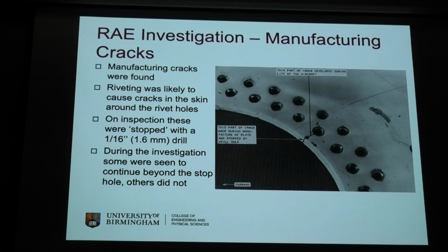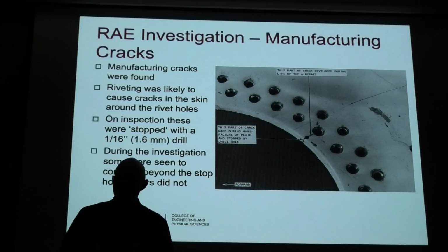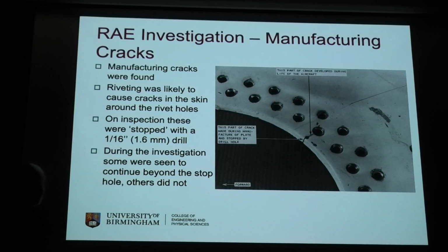And they found a number of things when they inspected it. Manufacturing cracks were found in a lot of pieces. And actually the DeHavilland specification said if you see a crack during manufacturing, you stop it with a 1/16 of an inch 1.6 mm drill. So if you see a crack, drill through the end and it'll be fine. Now some of those cracks stopped and didn't go any further, some didn't and the cracks grew on.